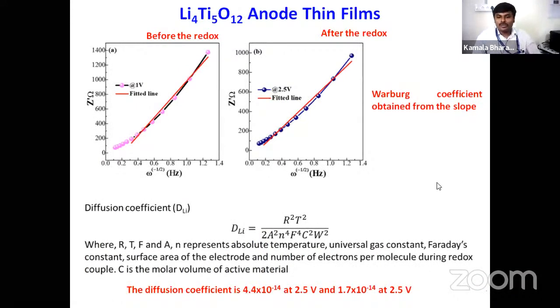So using the Warburg coefficient, one can find out the diffusion coefficient of lithium. So this is the equation where we can calculate the diffusion coefficient of lithium. These all are the constants, and W is the Warburg coefficient. Warburg coefficient can be extracted from the plot between the real part of the impedance and omega power minus half. So from the slope, we can find out the value of W, and we can calculate the diffusion coefficient. In the present case, the diffusion coefficient is found to be in the order of 10 power minus 14, which agrees well with the reported value for this material.